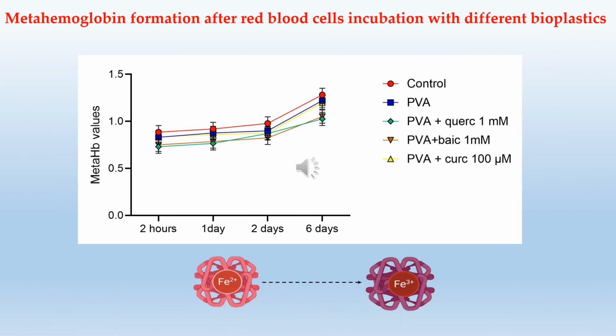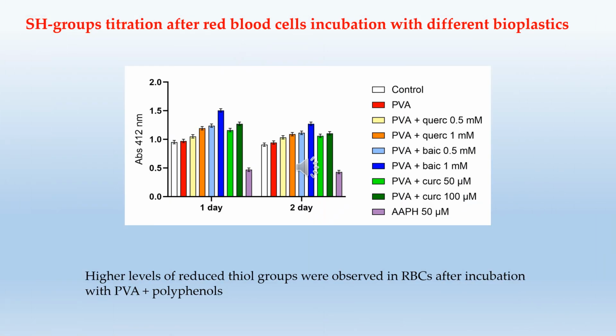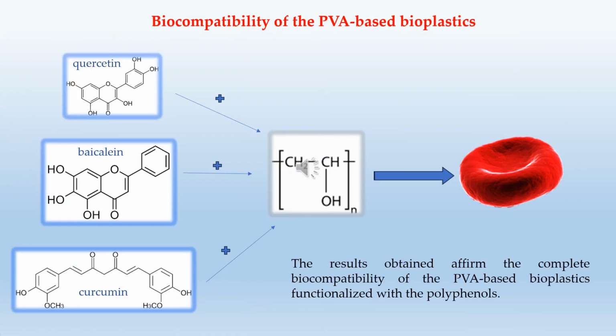The observed beneficial effect of the polyphenol addition is confirmed by the evaluation of the oxidative state of the RBCs. The graph shows a reduction in the percentage of methemoglobin in the presence of quercetin, baicalein, and curcumin compared to the control, even if the effect is more reduced in the presence of curcumin, which is similar to PVA alone. In addition, higher levels of reduced thiol groups were observed in RBCs after 1 and 2 days of incubation with PVA with polyphenol compared to the control. Then, the results showed that the presence of polyphenol has a protective effect on the red blood cell.